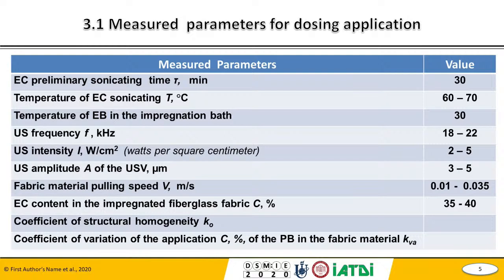The most important parameter was the fabric material pulling speed, from 0.01 to 0.035 meters per second. The next important parameter is the epoxy composition content in impregnated fiberglass. It was from 35 to 40%. Please, next slide.